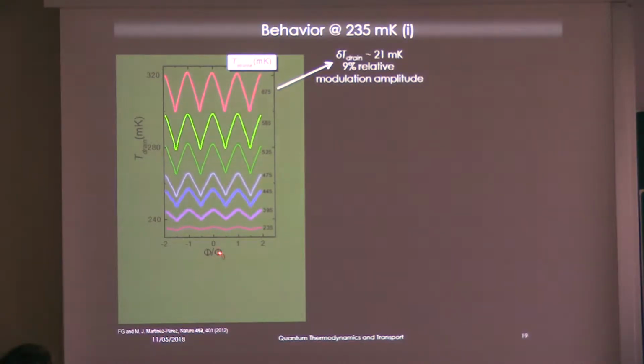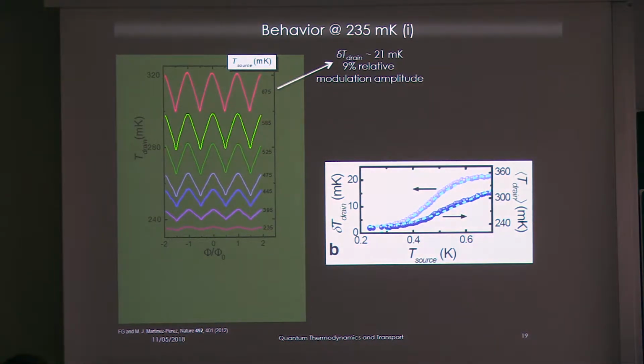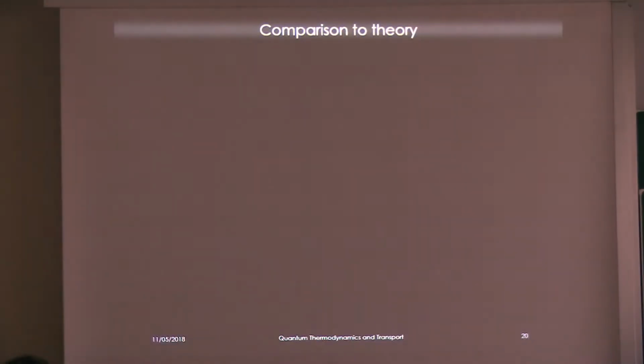Okay, increasing the temperature leads to an enhancement of the amplitude that we were saying before, that tends to saturate. Here we obtain the maximum, 21 millikelvin, that corresponds to 9% of relative modulation amplitude. Then the experiment was performed by looking at the evolution of the visibility, so the amplitude, the swing, as a function of the temperature of the source and the average temperature. So okay, they tended to saturate at a larger temperature.